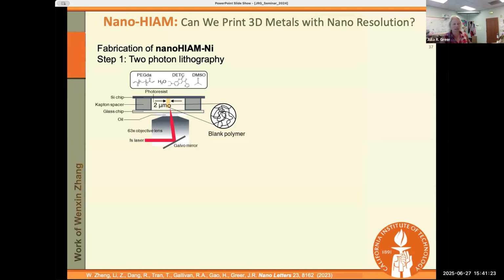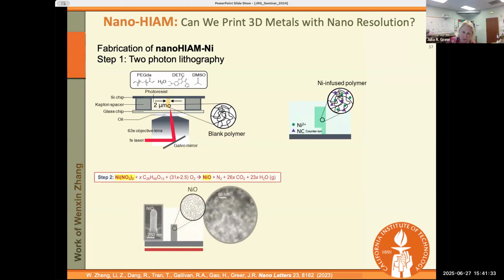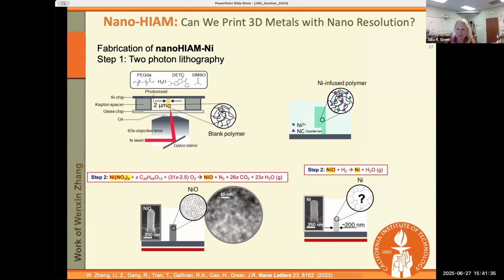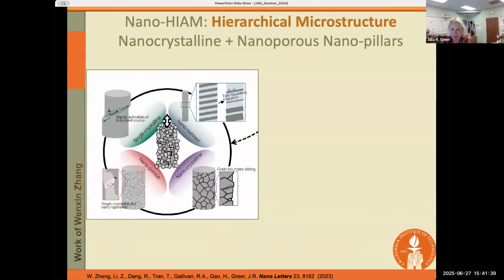Okay, this is just to show you that we can push this high-end approach into the nanoscale. And so not just the microscale, but the nanoscale. And this is where, of course, we're using 2-photon lithography. It's a slightly different cocktail. And my former student Wenxin was able to still infuse it with metal-containing salts. And we were able to get these tiny, 200 nanometer nickel, for example, nanopillars.